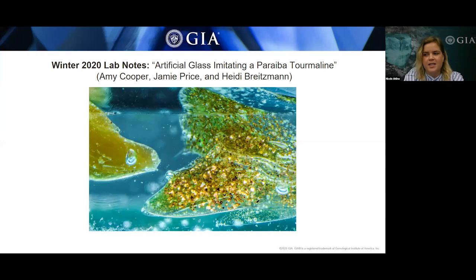So under microscopic examination, things seemed to be just slightly off on these stones. With the aid of the fiber optic light, both crystals showed trapped gas bubbles, a flow structure, and a distinct boundary where two types of glass, the one with the geometric copper crystals with that yellow body color, and then that host bluish green crystal, you can see where they were fused together.